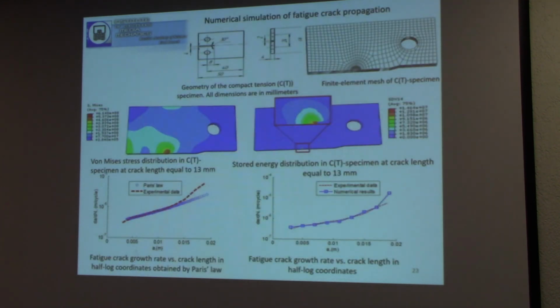We did some experiments. It's just an academic problem. We tried to solve the crack propagation, I guess, in titanium, no? In titanium, and we have a very good comparison between crack propagation and simulation based on our equation. But it's not a fully static simulation. We have a crack, make several cycles, calculate the energy for the last cycles, and estimate the energy rate. After, we take another crack and calculate it.